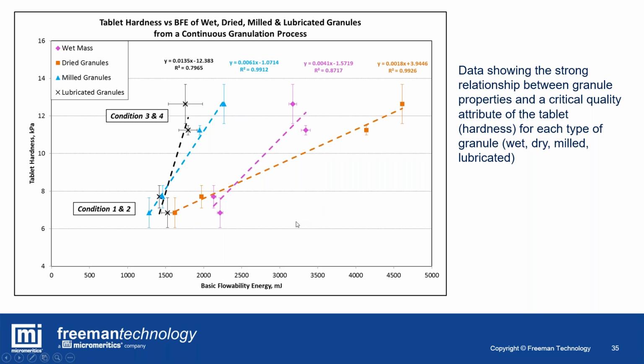And what that allows you to do as a process engineer, as a formulation scientist, is to assess that intermediate part way through the process. If you have a flow energy of, let's say, 3,000 millijoules, you know you're going to end up with tablets at around 9 kilopascals. And so you can manipulate this within your process development exercise and say, okay, I want wet granules with, let's say your target hardness is 10 kilopascals. I want wet granules with a basic flow energy of 2,800 millijoules.